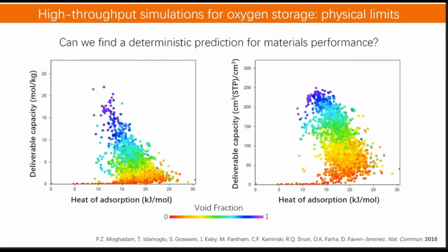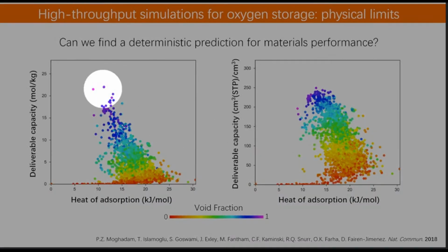This is something that is clearly shown in this screen. The problem is that this is a multidimensional problem, and if we only pay attention to one variable, this doesn't work. But as soon as we include some colors in these different representations, you can see something that works much, much better. We need not only an optimal interaction with the material, we also need an optimal void fraction. And this is particularly important when we are talking about the volumetric capacity of these materials: how much gas we can absorb per unit of volume.